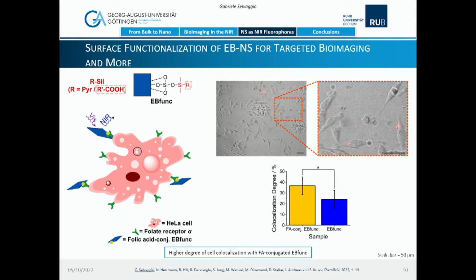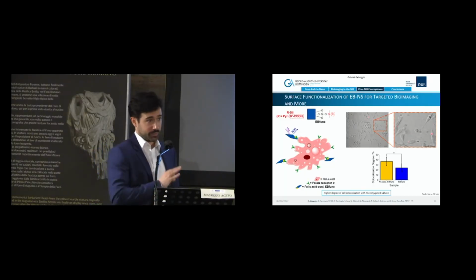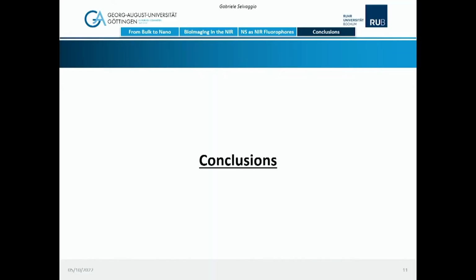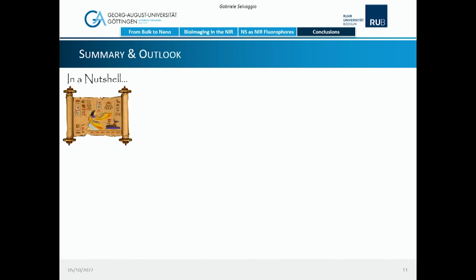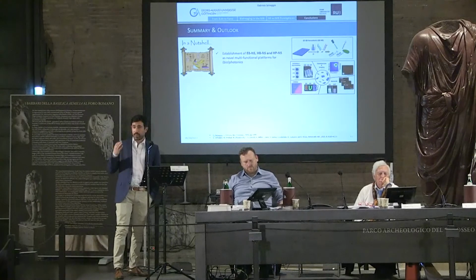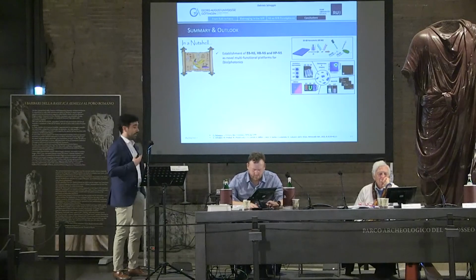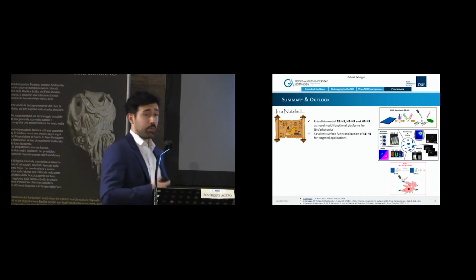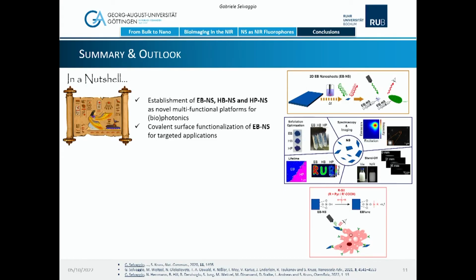And given the versatile chemistry of this approach, this opens up to several applications in the targeted direction, not just bioimaging itself. And with this, I am concluding. I hope I'm good in time. In a nutshell, what did we do? So we were able to establish nanosheets of Egyptian blue, Han blue, and Han purple as novel multifunctional platforms for biophotonics. And we were able also to covalently surface functionalize the surface of these nanosheets for a plethora now of targeted applications. And since we were in Bluenet, we have to keep an eye, of course, also towards the future.